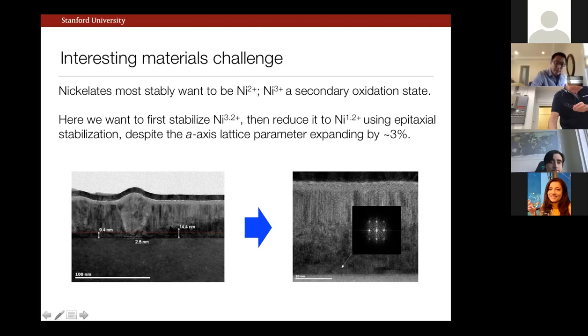It looks terrible, and that's the point in some sense. There are all sorts of decomposition phases, secondary phases, and you can hardly see it here, but just a sliver at the interface turns out to be this infinite layer structure. So with considerable effort, Denver could then get this to the point where uniformly in the first few nanometers at the interface, we could indeed stabilize this infinite layer structure. You can see this in the Fourier transform. This tetragonal distortion corresponds to this planar contraction. But still, the vast majority of the film volume, if you will, is some rather messy unknown structure.